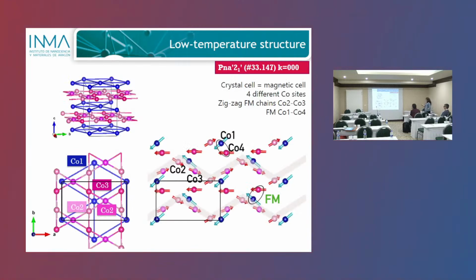So this is a view from above. You can see here the triangular layer. These are cobalt 1. They are further apart. And then you have the Kagome layer on top, if you look at it from the z-axis. And you have the 3 remaining cobalts in the cell. And the magnetic structure is quite complex, but you can think of it as, I don't have enough contrast here, but you must believe me that here you have a zigzag chain running that way along the a-axis. And in this zigzag chain, they are coupled ferromagnetically. And then you've got the triangular cobalts and cobalt 4 that are also coupled ferromagnetically between them. So this gives a net moment only along the a-axis.